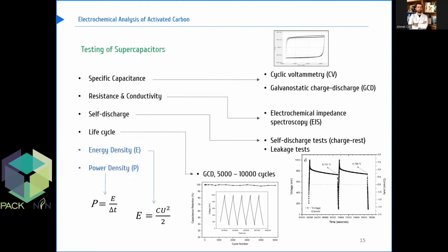The Nyquist plots, or the Bode plots, obtained from the electrochemical impedance spectroscopy data are used to determine the combined resistance: intrinsic resistance of electrode material, ionic resistance of electrolyte, contact resistance between the electrode and the current collector, electrode conductivity, and charge transfer resistance.